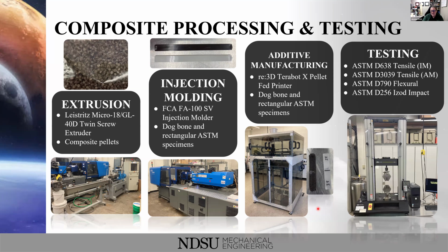And then we did some testing on these. In this work, we're focused mostly on tensile testing, flexural testing, and then IZOD impact testing. We do want to look at compression testing. As you can imagine, that's very important when it comes to habitats, structural materials, that type of thing. We unfortunately did not have the grips in place at the time of this work to do the compression testing. We did print the specimens, we just didn't get to test them within the labs. So we do plan to do that at some point in time.